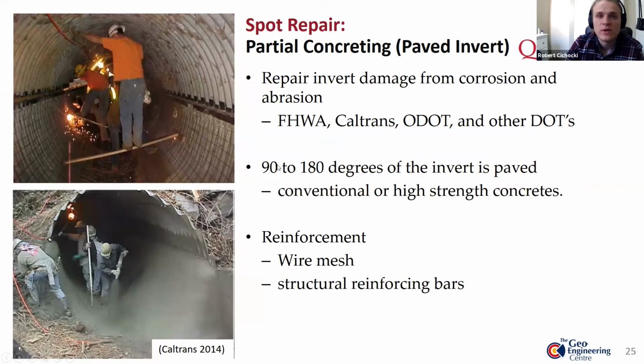Generally, we see rehabilitations covering 90 to 180 degrees of the invert, and either conventional or high strength concretes are used. As you can see in the picture, we have L angles that are welded across the spring line of the structure, as well as a wire mesh being used for light reinforcement. In this case, the wire mesh is actually being spot welded to the structure, at about a 4-inch spacing circumferentially, and every 30 inches down the length of the pipe. Further, before applying the concrete invert, they also grout any voids that are present in the structure. After the voids are filled, then the cement mortar is applied.